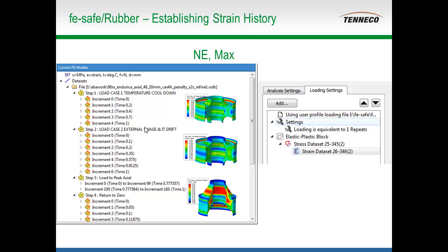And then also most suspension bushings get a post-molding forming process where the diameter of the outer tube is what we call swaged. It's basically to relieve what is essentially tensile strains from the thermal shrinkage and put it into a state of compressive strain. For those that do model rubber or work with elastomers, tensile strains are the worst for fatigue crack growth. And then over here we're highlighting, and down here, that the FE-safe rubber routine was only examining the cyclic axial loads in this case.